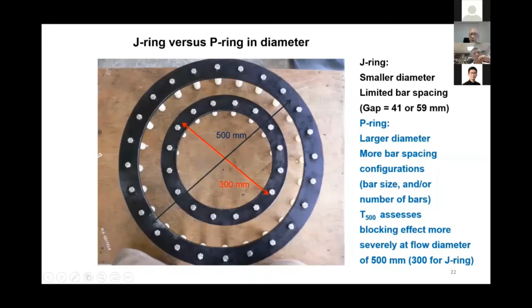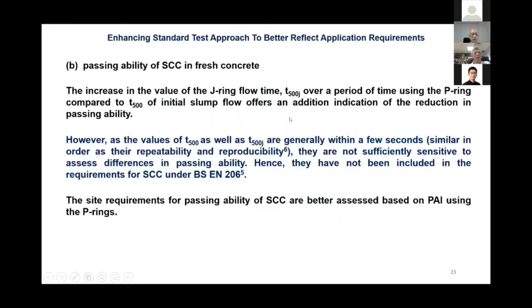That means we are now able to look at the time taken to flow from the slump cone to 500. A bit longer time, so the number of seconds is increased and we have a better judgment of the actual thing in relation to the degree of uncertainty. So you can see, the passing ability of the fresh concrete over the P ring, the flow time, the T500 as they call it, is much longer compared to the T500 in the J ring. So you can see that the P ring has a lot more flexibility.